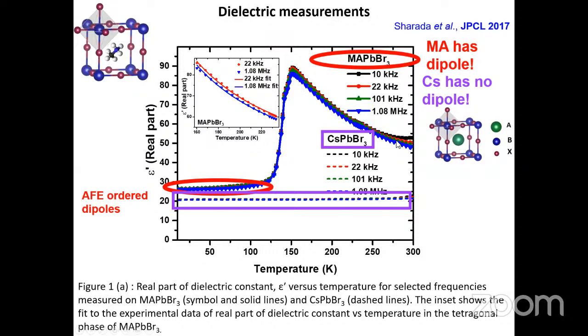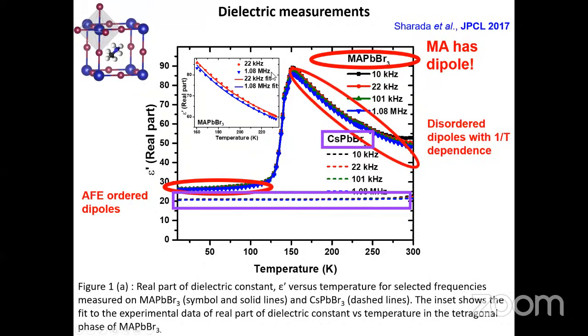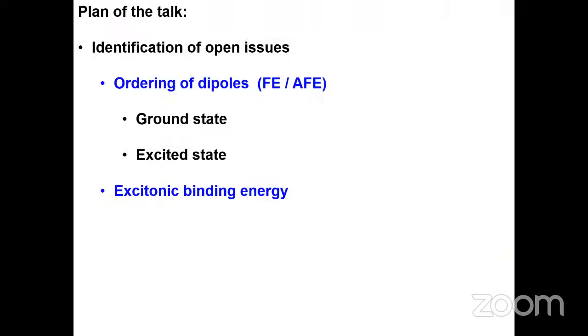But then at this temperature, I find a huge 1/T dependency of the dielectric constant that tells me that the dipoles are rotating freely. This is like a paraelectric state where dipoles can rotate and respond freely. And in fact, our theoretical simulation tells us the rotational time scale is about 5 to 10 picoseconds. So they're rotating very, very fast. There are many consequences of that, but I'll not go into them today.